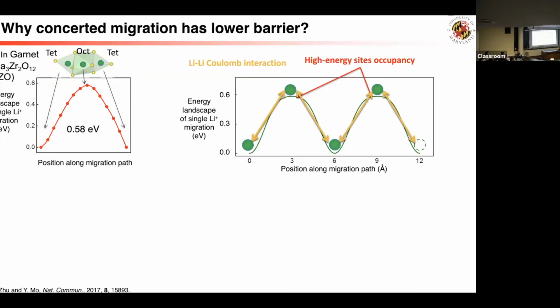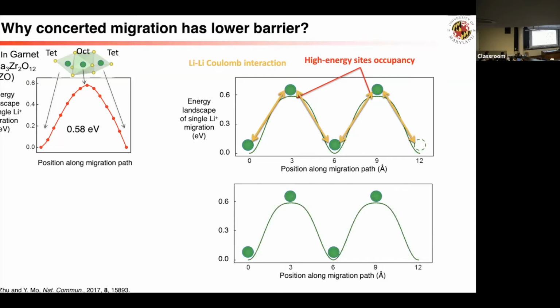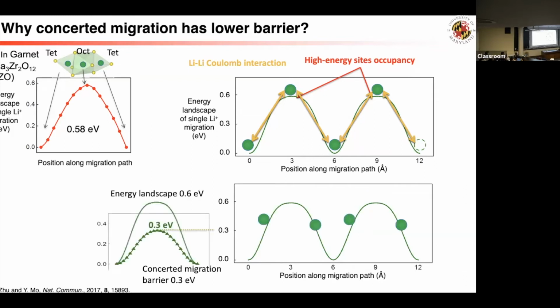So we take the barrier the same as lithium garnet, about 0.6 eV. So you would think that if only 1 lithium ion is migrating, the barrier you need to overcome is 0.6 eV. And we find that if you have this kind of ion arrangement with repulsion between them, the 4 ions migrate together, and as a result of this multi-ion migration, the barrier is actually decreased to 0.3 eV. Four ions moving together only have 0.3 eV, a lower barrier.